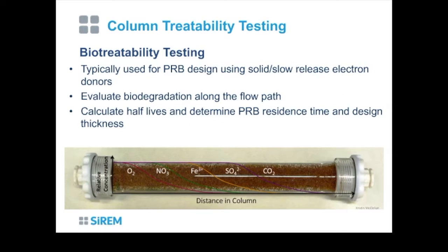So for biotreatability studies, columns allow us to test for PRB, so permeable reactive barrier designs, where you're looking at solid or slow-release electron donors. And you can see the gradient of conditions where, at the front of your column study, you might see reduction of any aerobic conditions or oxygen, then nitrate-reducing conditions, iron-reducing, sulfate, and methanogenic conditions ultimately. It allows you to evaluate biodegradation along the flow path, calculate the half-lives, look at residence time and design thickness. So it can be quite a valuable tool to providing design data.